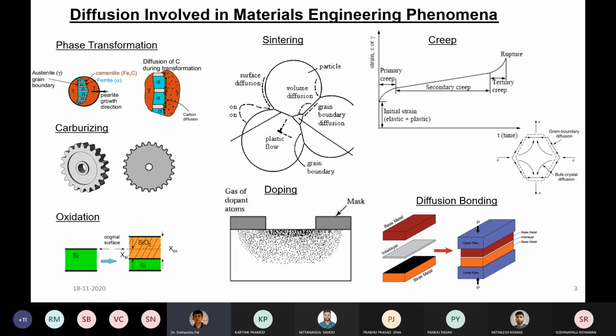So when the sintering process is occurring, surface diffusion, volume diffusion, and grain boundary diffusion are dominating. Since these are dominating, that may cause plastic flow of the material in the particle, the interparticle plastic flow. And that actually makes the sintering process done. So this is the important phenomenon: diffusion is important with respect to the sintering process also.